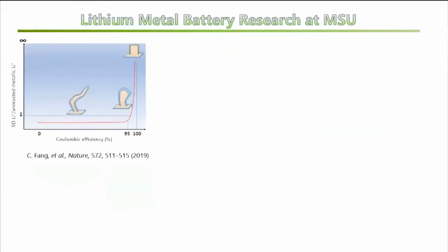Our previous research built a quantitative morphology-performance relationship. It tells us if the lithium grows as whiskers or dendrites during the charging process, the cycling efficiency and cycle life of our battery can be very low. However, if we are able to achieve a fully dense lithium deposition with the ideal columnar morphology, we can significantly improve our cycling efficiency and get long cycle life. Then the question is, how can we get this ideal morphology?